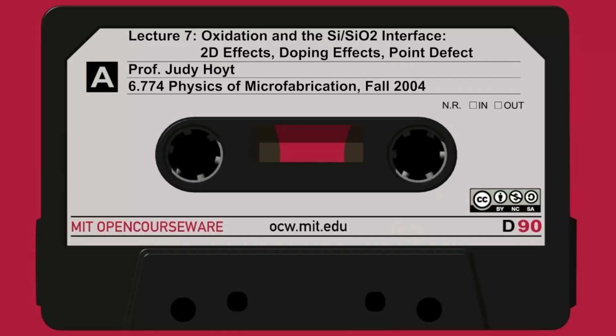And not only that, if you look back, I'm going to go back a couple slides to, say, slide 12. When I take the nitride off and I go to use this as processing my chip, the surface is not very planar. So I have to do photolithography now on this surface. It's not very planar. I have this big oxide hump sticking up here in the field, and the field is much higher here. Look at the field. It's up here at 0.3 microns above the original surface. So I got this big mountain sticking up over in the field.